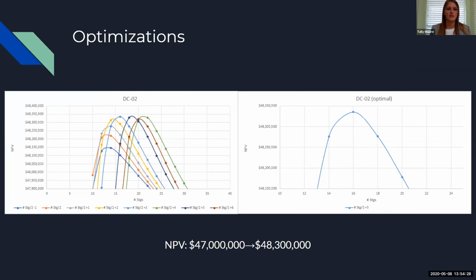After optimizing the reactor, we decided it was best to work backwards in our system to optimize the rest of it. So we decided to start with distillation column 2, which is the top column coming off of the fractionator. The way this was optimized was by coupling the number of stages with the feed stage location. And as you can see on the right, we pulled out the optimal so you could see the visual better. It was at 16 stages with the feed stage location of 11. And this took our NPV from 47 million to about 48,300,000.